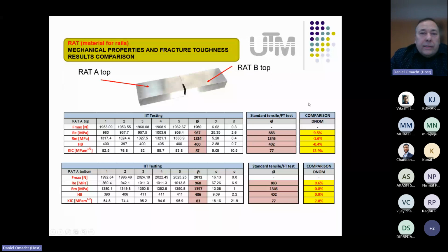How is it with the high strength steels? This is high strength steel. You can see two parts of the sample, part A and part B, and we measured fracture toughness, and you can see the average value is 87, and from the CT test was 77. So the difference is about 12% at part A, and at part B it is about 7.8%. If we realize how big the specimen for the CT test is, and we compare it with a very small imprint, in my opinion, it is a very good result. Accuracy of the fracture toughness at this moment is up to about 20%.